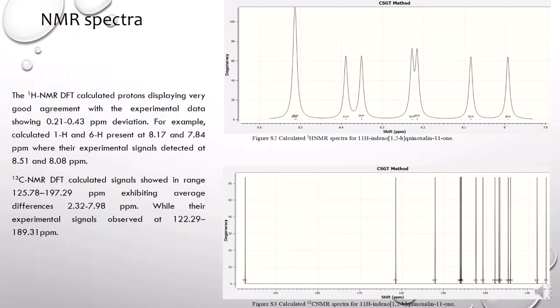8.08, and the carbon 13 calculated shows in range 125.78 to 197.29 with average difference 2.32 to 7.98, while the experimental is in range 122.29 to 189.31.